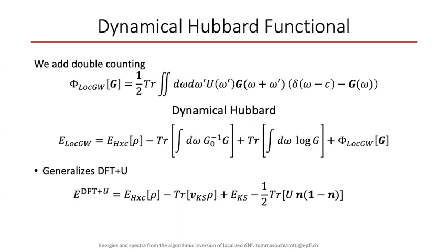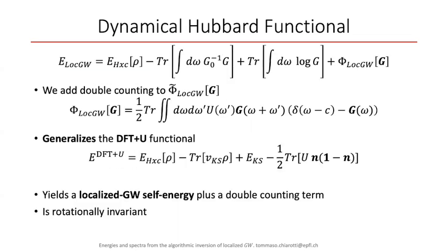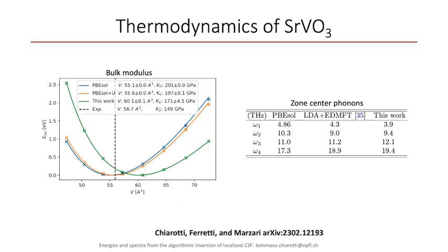Okay. Yes. Because I wonder whether what you find in the energy, the wrong lattice constant, could be due to a non-conservation of the electron number. Indeed, this is for sure correct, because the formalism is particle conserving, but since we did a non-self-consistent calculation, these are not particle conserving, and this is the reason why the lattice parameter is wrong. But maybe if you renormalize by the number of electrons, this becomes correct. It's possible. Since it's a very stepwise process, I want to implement the self-consistent thing and then see that the lattice parameter goes back to the correct DFT+U value. But you're right, that can be an idea.